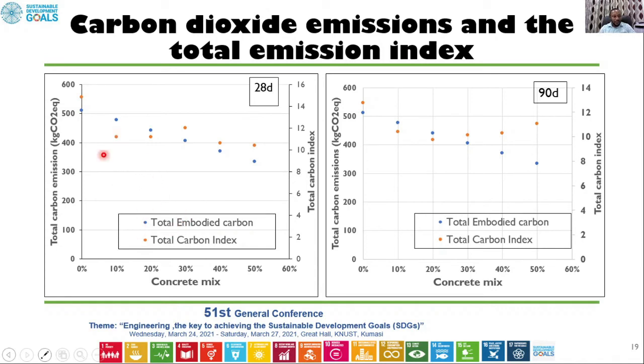So look at the trend. The 0% is without the pozzolan, but then you realize that as we incorporated the pozzolan content, both the total embodied carbon and the total carbon indices were decreasing, and the decrease was very high when the pozzolan content was also high in the concrete mix. It was very similar to what happened at the 90-day curing period.